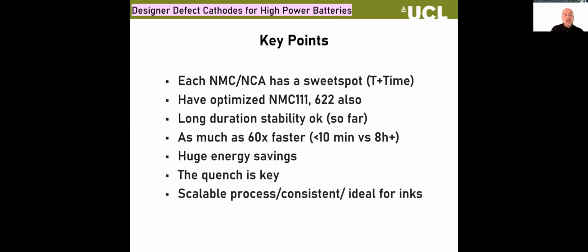So the key point here is that every NMC, in fact we've done this with other NMCs, with 111 and 622, every NMC or NCA material has its optimum time and temperature, and it's usually under 10 minutes. It is under 10 minutes in every single case, which is what our patent is covering. It also works with sodium ion chemistry, and it probably will work with a whole load of other chemistries where you can do a conversion from a bottom-up precursor in seconds or minutes. It works with other stuff, but I can't talk about that because we might file a patent on it. But the point is, it's orders of magnitude less energy in terms of time spent in the furnace.